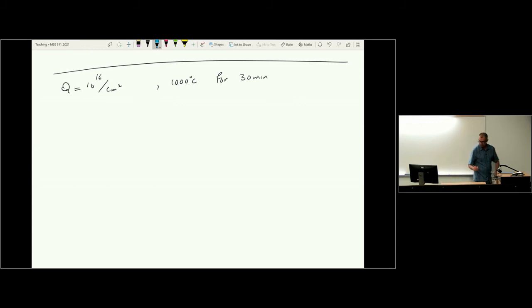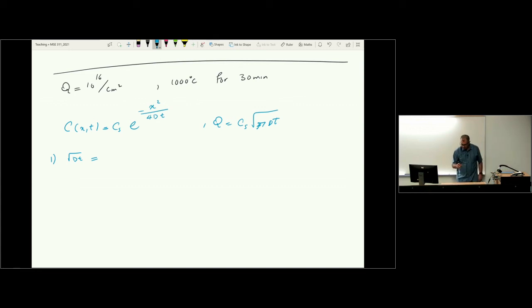So I go back to here, I can see that C of x and t is equal to Cs e to the minus x squared over 4Dt, and the areal density is Cs times square root of pi Dt. Okay, so these are the equations that I have, and I calculate Dt first, the characteristic diffusion length. So part 1, square root Dt, I calculated. It's the same as the previous problem, except it is half an hour. The previous case it was 1 hour. So we go and calculate it again.